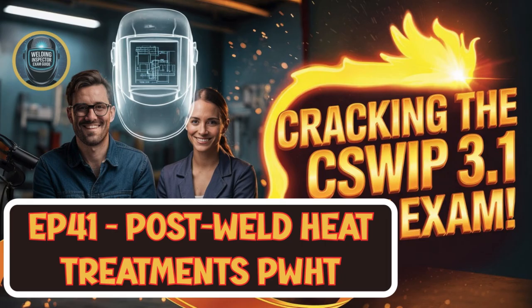There's also a less common but important case where you might actually normalize a joint with heat treatment to specifically restore toughness in that HAZ. But you have to be careful there. That specific treatment can really knock down the strength of the weld metal itself. So the filler metals, the welding consumables, they have to be chosen very, very carefully right from the start if you plan to do that. Right, so it sounds like PWHT isn't just about the weld bead itself, but the whole assembly, the weld, the metal next to it, making sure everything is, well, stable and ready for whatever its job is.